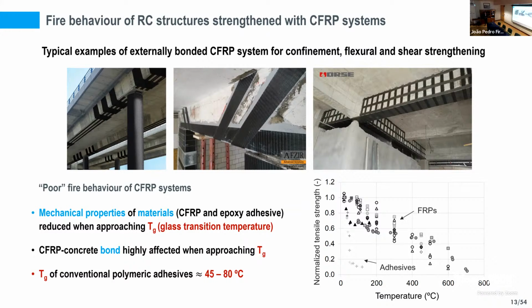are highly affected. Here on this picture, on this corner, we can see the reduction of the material properties of both the FRP materials and the adhesive. And we also can see that the adhesive material is much more affected by temperature than the FRP itself. So, as the adhesive is responsible for the connection of the FRP material to the concrete surface, the bond behavior is highly affected. So, when we started investigating this topic, the research on it was relatively scarce, and the